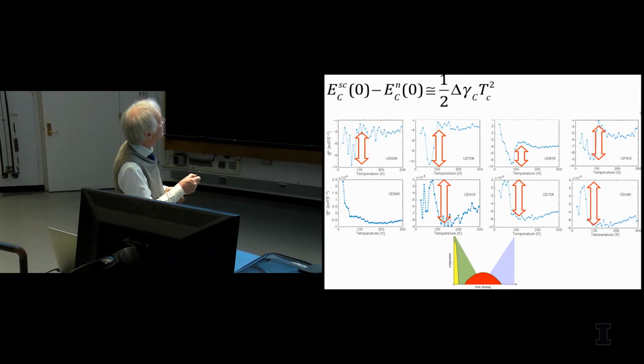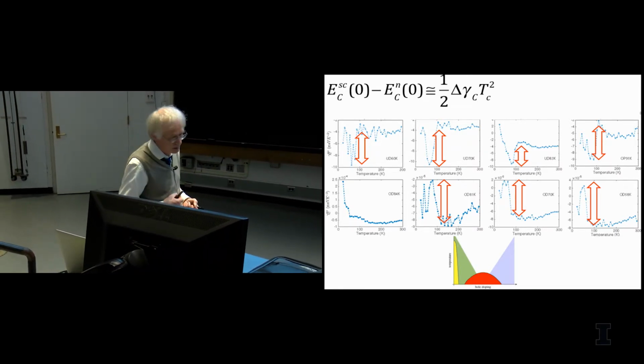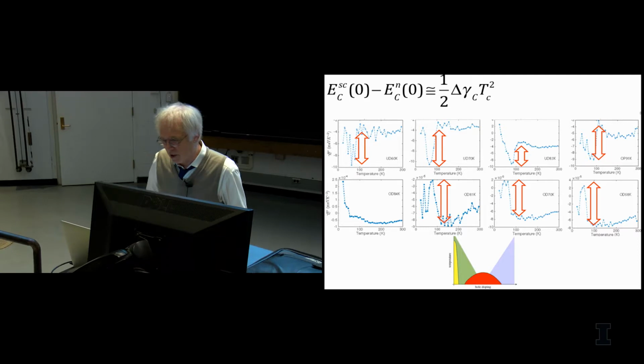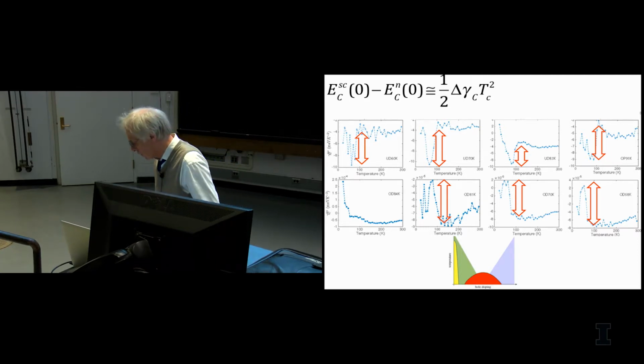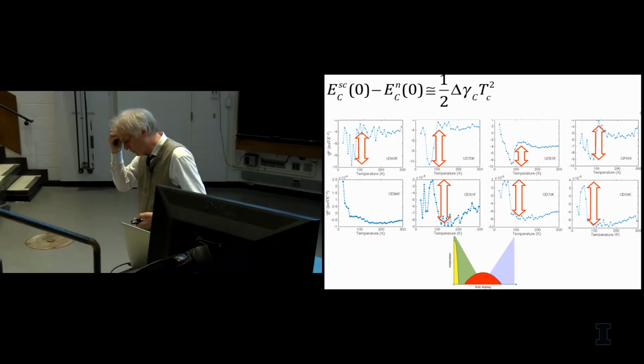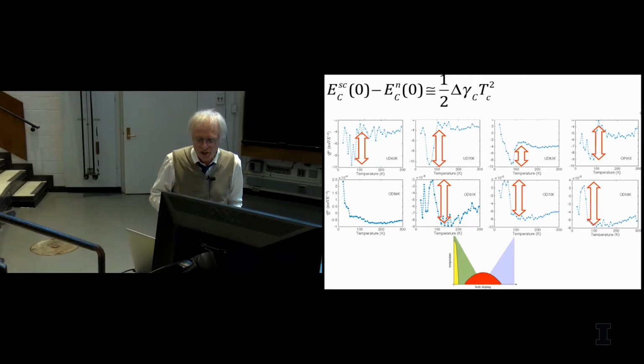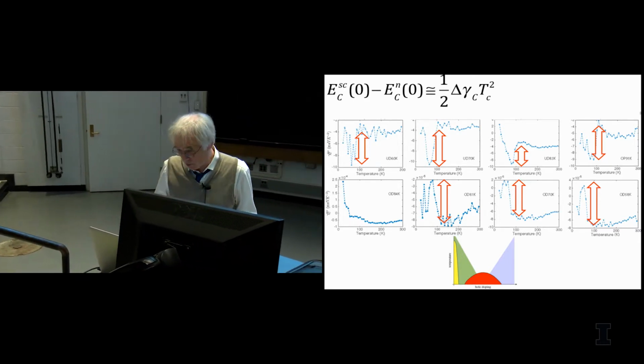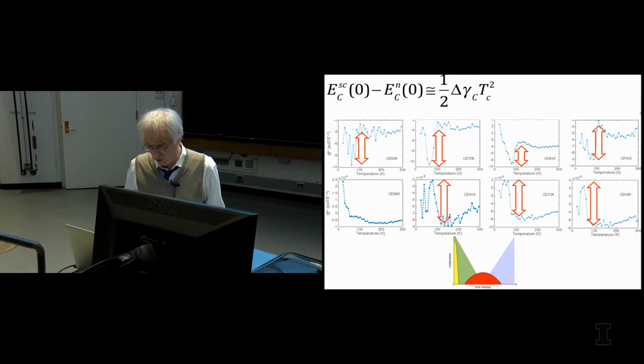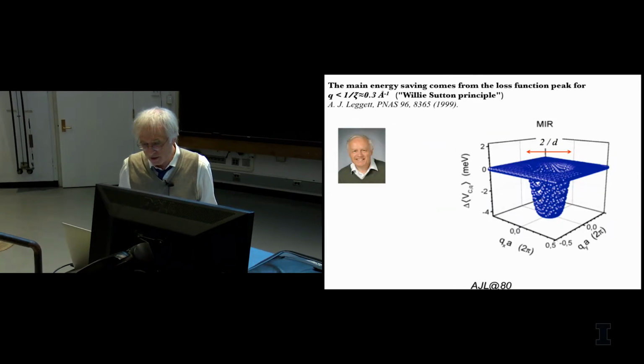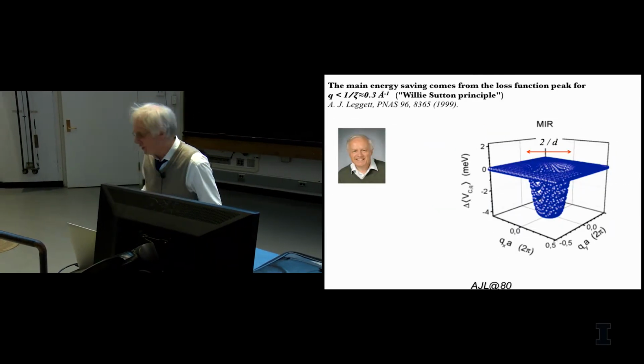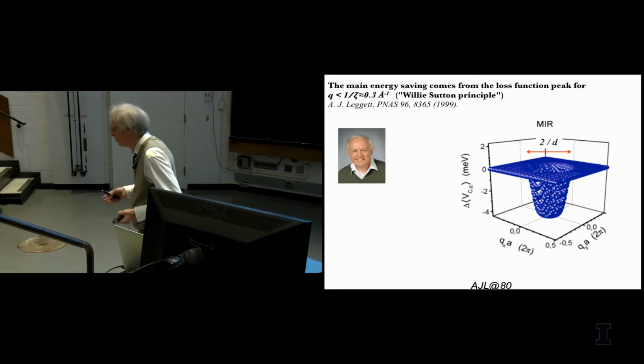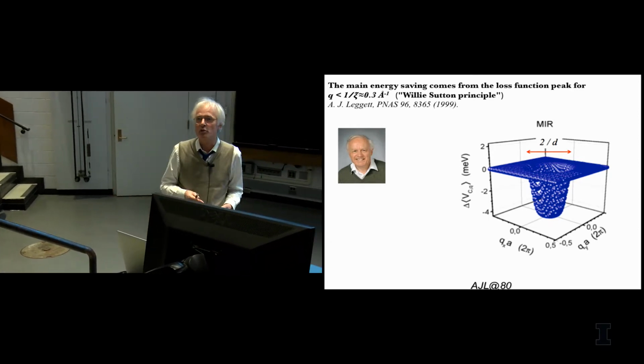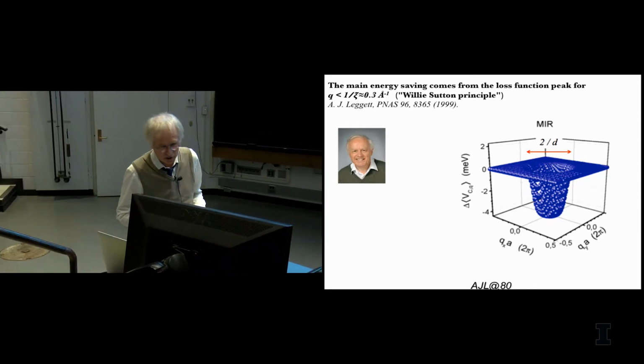You can also look at the derivatives, and using those derivatives, you can actually, using a small trick, make a reproducible estimate for all the different samples about this condensation energy with a weak assumption about what the temperature dependence is below of the normal phase. So that's what I did. Then you have to say, okay, what does it mean now for the total Coulomb? Here we look only at one Q value, but you should, of course, integrate over all Q values.